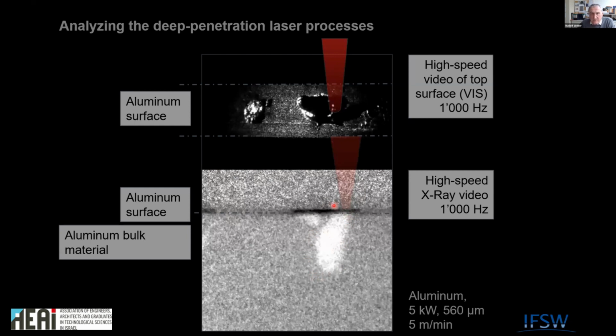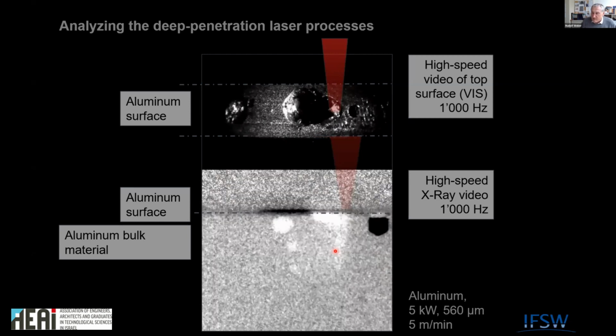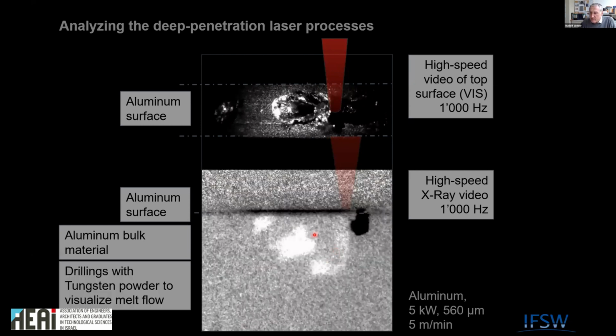So whatever is brighter, material is missing. And what you can see is the capillary I've explained just before. And here the laser beam is coupled into the capillary and the system is heating up. And that's what you can see now, that it's very fluctuating. We can see that whenever it's bright here, it's a kind of bubble or a kind of pore finally. And you might also see that the contrast is not very good. That has something to do with the complete X-ray system.